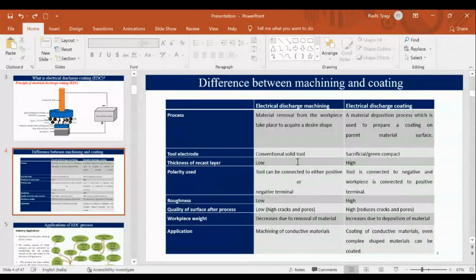So thickness will be low in EDM, because in EDM the recast layer forms. Recast layer is the particles that are not flushed away with the dielectric when the machining takes place. So thickness will be very low. Some particles are left inside the spark gap, and they form a layer when they solidify during cooling down, that is the recast layer. But in electrical discharge coating, we are using the green compact tool, so a high amount of thickness is obtained because material gets deposited.